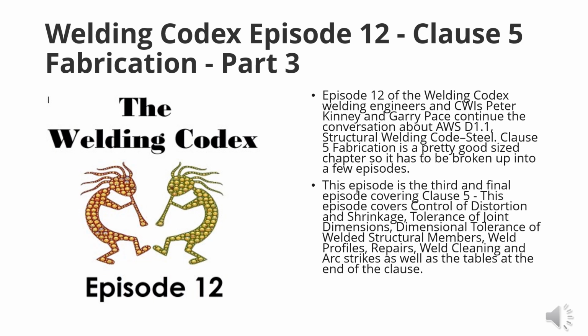When you're dealing with heavy plates or big jumbo sections that are 3 inches or greater, if you can't close the gap after straightening or moving things around, you can get 5/16, but you have to put some backing in there. What I've normally seen for that is subarc flux has been a good one to put in. Or you can also weld up the backing and basically make something that the fillet weld can bite into. Where I've mainly seen this is on big girders, where you have plate and the tolerances for A6 allow some waviness, and you have your web going on your flange, and you may need to build up that area to still meet that 5/16 requirement. That's the main thing that addresses right there.